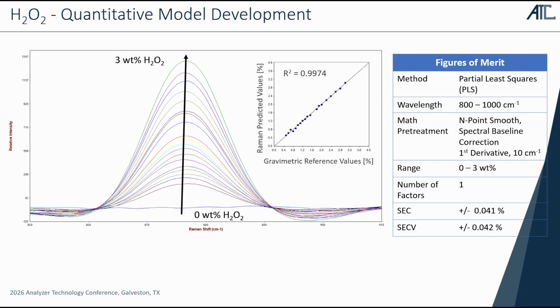And then we used the data, ran them through chemometrics to build those models. And some of you might look at the R square and say 0.9974, that's not good enough because we want 0.9999, because that's what we do maybe in chromatography. But for spectroscopy, it's very important to look into how well this model predicts. So our calibration error, cross-validation error, prediction error in comparison to the error of the reference technology. And so looking here at the SEC, SECV, calibration and cross-validation error, we are looking at 0.04, 0.05% plus minus as a predictive error in this range, which is good. We can add more data, make it more robust, but it definitely shows the feasibility of this application, and it shows that it's a direct peak that we use and not just some baseline shifts like in other spectroscopy technologies.